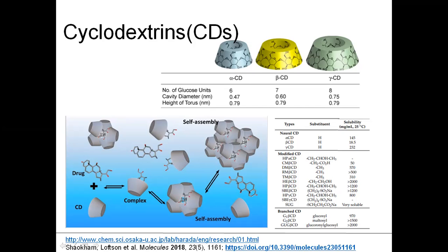However, natural cyclodextrins have a tendency to self-assemble and form aggregates in aqueous media. Cyclodextrin aggregation can limit their solubility. Through derivative formation, it is possible to enhance their solubility and complexation capacity, but these depend on the type of substituent and degree of substitution.